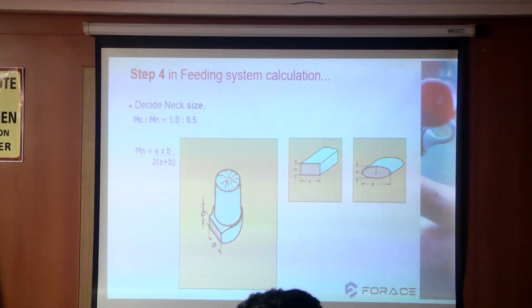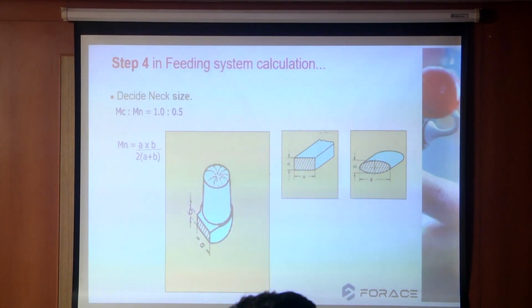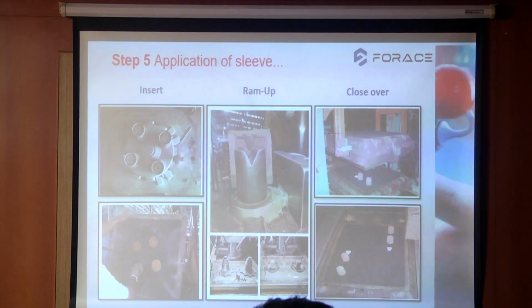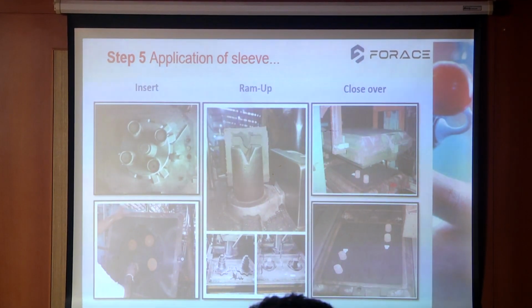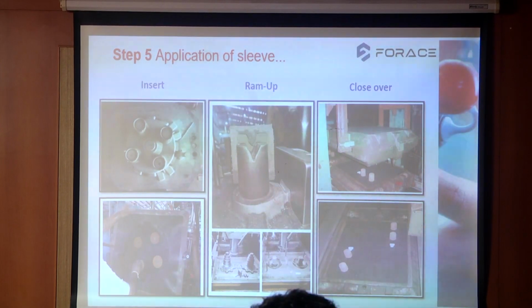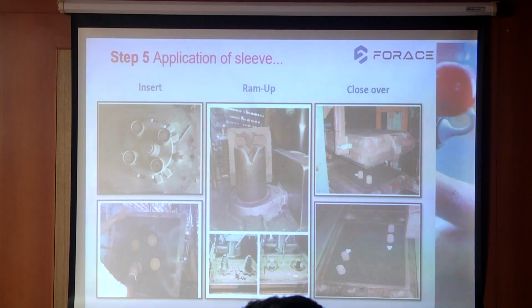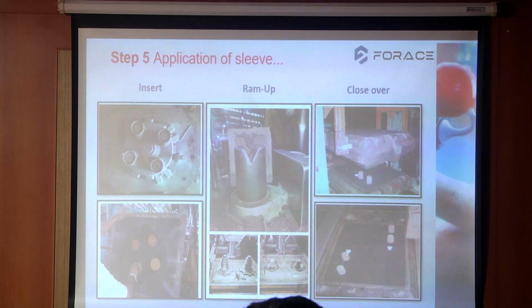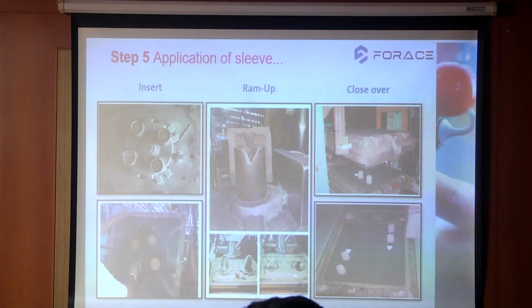Then you have to finalize the neck of the risers. Then you have to decide how you are going to apply the sleeves. There are three types by which you can apply the sleeve. First one is insert application into the mold, that after the mold has been prepared, you can insert the sleeves. Ram up application, that before molding you can put the sleeves on the pattern and they will get rammed up in the mold. And the close over method, like you are putting the cores in a mold, in that way you can place the sleeves on the drag pattern and the pattern will get closed.